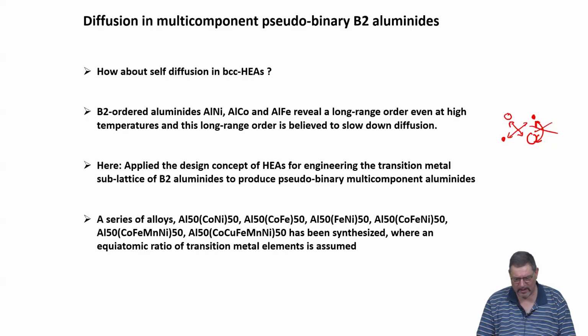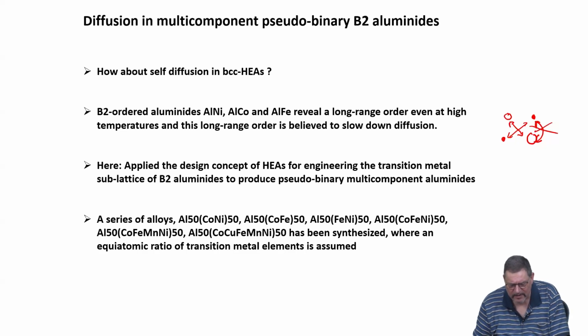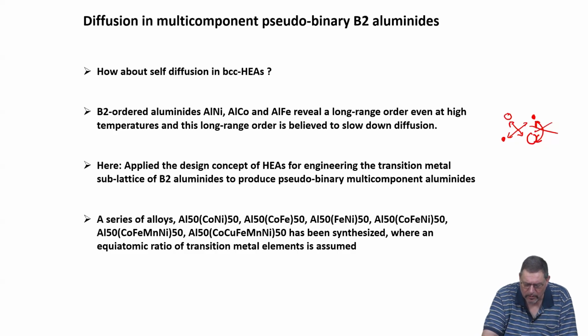and this makes diffusion slower. And if we now apply this design concept to these aluminides, we need to think of sublattice alloying. So we need to introduce different elements and not just one on each sublattice to get pseudo-binary multi-component aluminides. And so we did this for this series of alloys where we basically have aluminum 50 as the base component for one sublattice.